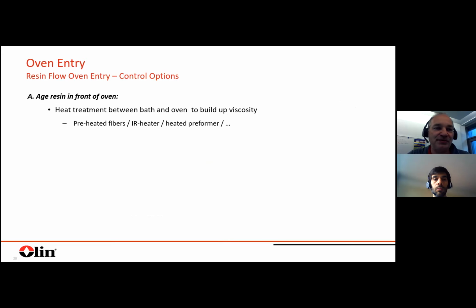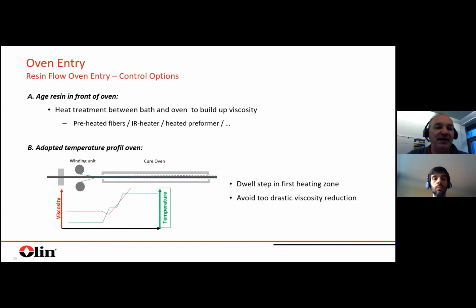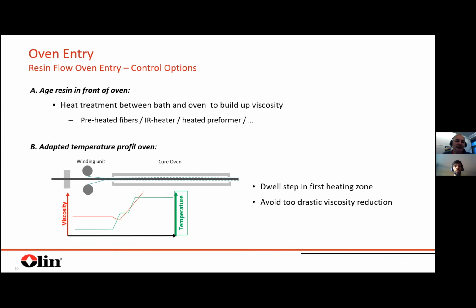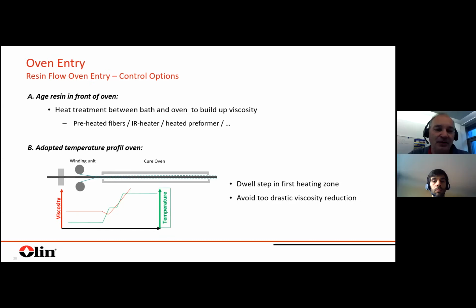So two options from our point of view, from the resin point of view. As mentioned, the first would be to age the resin in front of the oven by some heat treatment on the way, just to build up some viscosity, so that the minimum viscosity will not be too low. Or you have a specific cure profile in your oven, so that the first zone is not at whatever 200 C, but maybe you start with 120, 140, just so that the viscosity goes down not too much, and then the viscosity is built up. So this is a way to minimize this effect or avoid it completely. This also has to be looked at depending on line speed and so on. But this is something which is quite effective to overcome this.